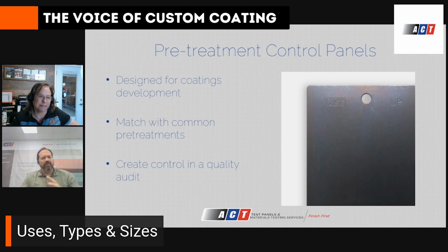And it's really a function of a whole system, because the powder coating can only do so much. Right. The pre-treatment has a big effect on that, as far as how things creep. Because what happens is you get the rivers of water. The salt comes in and starts to break down the lower surface, and then the rivers of water just go through, and you start to get delamination from there. Yeah. If the pre-treatment's holding, you don't get those rivers of water going through, and that holds that line really, really tight. Custom coaters see it. So, they've seen some panels like that.